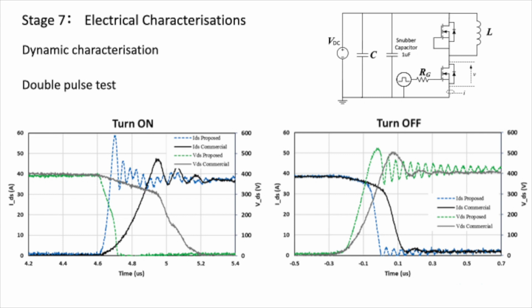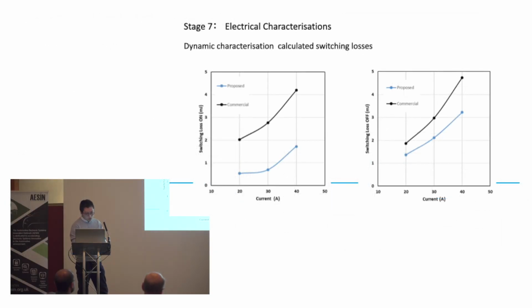We want to know how much the energy can be reduced by using this proposed module. So we simply multiply the voltage and current and integrate the power over time. So we get this calculated switching loss. For the turn-on and turn-off at different currents, we got this comparison graph. As you can see, for the turn-on, we have just 1/4 to 1/3 of the switching loss of the commercial one. And for the turn-off, we reduce the switching loss by about 25%.